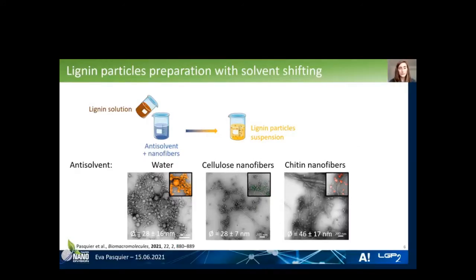This led to lignin particles with a smaller size distribution. For example, here with the cellulose nanofibers, you can see that the particles are way smaller, however they are still aggregated. And when we added some chitin nanofibers, you can see here the lignin particles are actually well dispersed on the nanofibers. So we have adhesion properties, and we wanted to look at